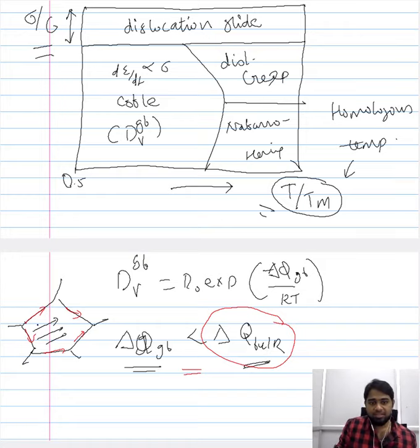So that means this diffusion within the grains is also possible, and once you have diffusion within the volume of the grain, or the bulk of the grain, then you have a shift from the Coble creep mechanism to that of the Nabarro-Herring creep mechanism. Now ultimately, when you have the combination of average stress and average temperature, you have the dislocation creep mechanism.